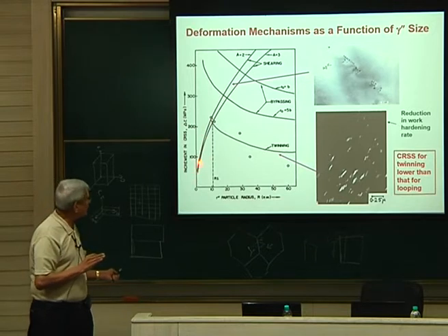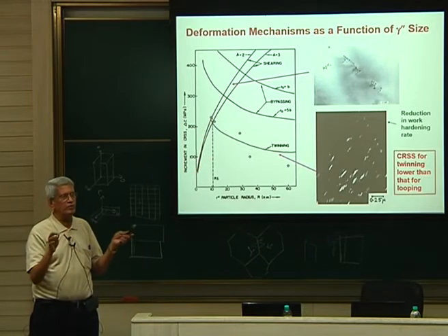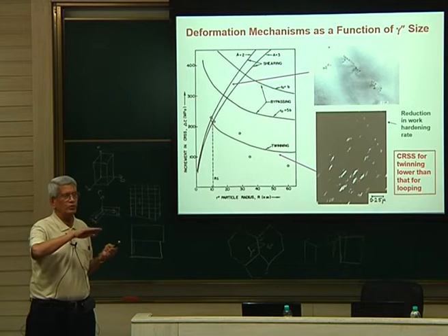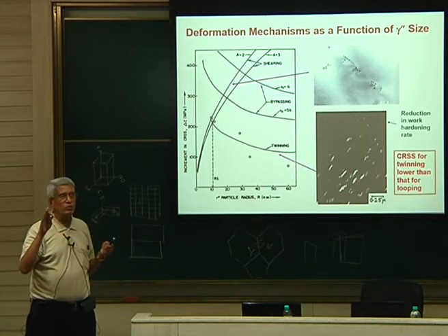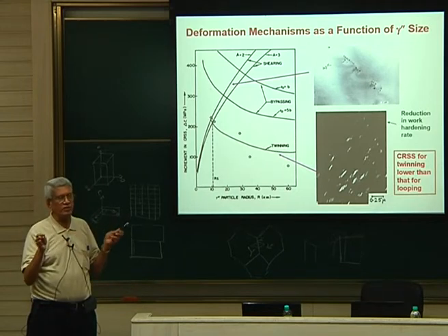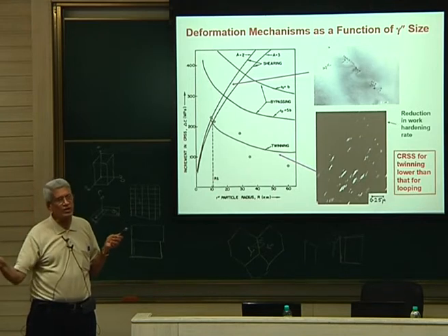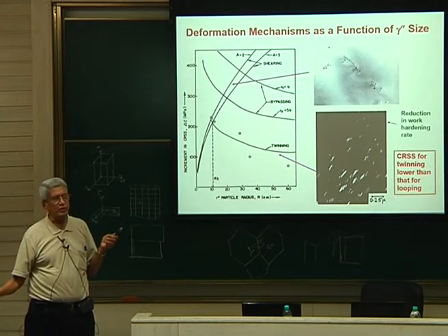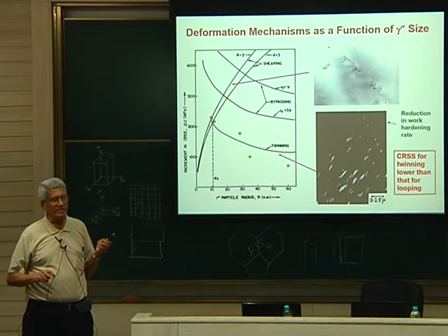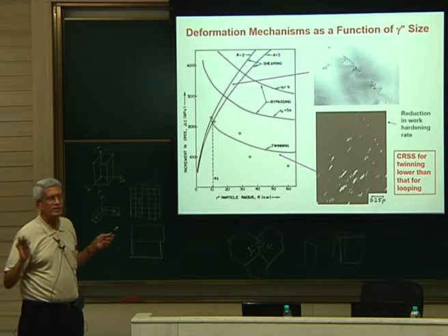As the nuclei form and start growing, once the critical size of the nuclei has been reached, all of them go only in one direction; they do not dissolve. When do they dissolve? During the coarsening regime, the fine precipitates dissolve and the large precipitates grow at the expense of them, and that is what we call the coarsening regime. There the volume fraction remains the same, the number density comes down. In the growth regime, the number density in principle should remain the same, but the size should increase. You understand that?